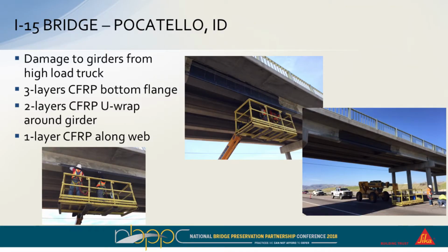They didn't want to shut down the bridge for too long a period of time, so they can essentially get this done in probably about 6 to 8 hours total. The design for this was 3 layers of the FRP on the bottom, 2 layers as a U-wrap, and then 1 additional layer along the web. That was to restore the strength that was knocked out by the strands.